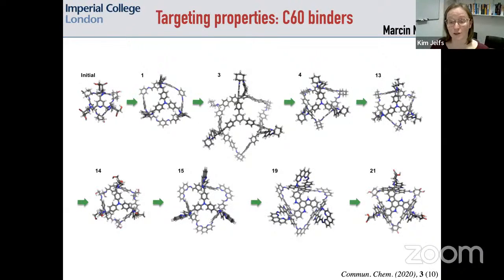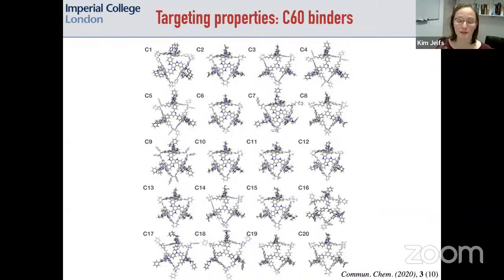By 3, it's got too large. And then it settles down thereafter in the generations on cage sizes that are much more sensible for hosting a C60. And so instead what you're seeing is that cages are getting selected for where there are switches of the precursors that will help to strengthen the binding energy for the C60. And then we would run it multiple times to sample different outcomes. And here is then our top 20 systems that were predicted with a 4+6 topology to strongly bind C60.